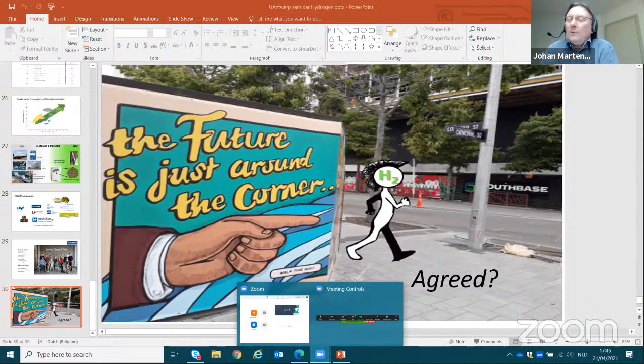Such a clathrate structure, if you stabilize it in a hydrophobic, and I emphasize hydrophobic, environment, in nanopores which are hydrophobic, then it's much stabilized. So this hydrophobic environment exerts a pseudo pressure on that phase, and that keeps it stable. That's amazing, the gains you generate by hydrophobic. That's also the topic of my ERC Advanced Grant. It's the behavior of water in hydrophobic pores.